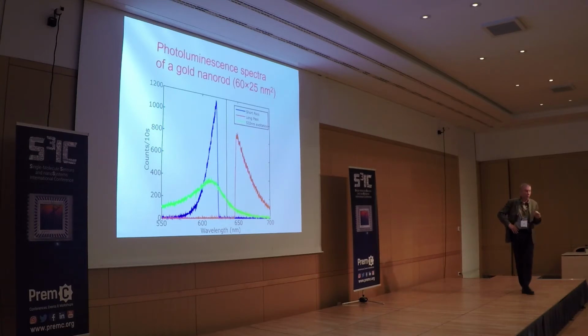If you do it at 0 temperature, you send a photon with h bar omega. You know that you can only leave energy in the material. We come out with a photon omega prime, which has to be less than omega at 0 temperature, right? But at room temperature, it's possible to go out with more energy. That's anti-Stokes. And of course, this tail here, or this wing of decay of the line, tells you something about the temperature of the particle.